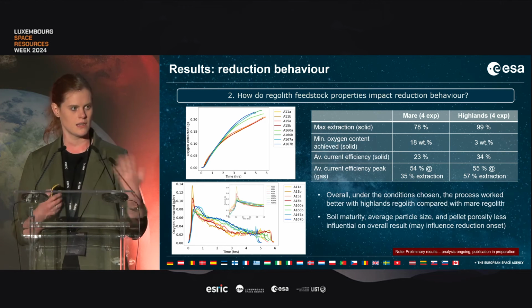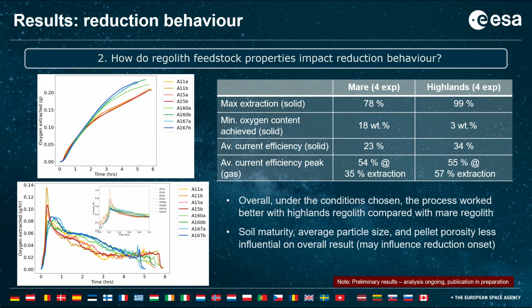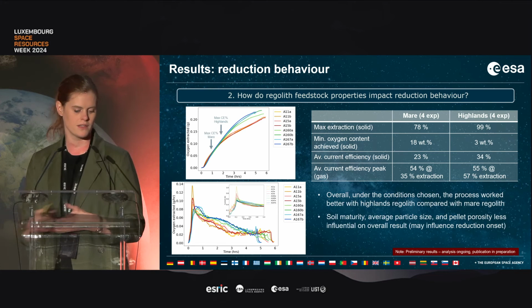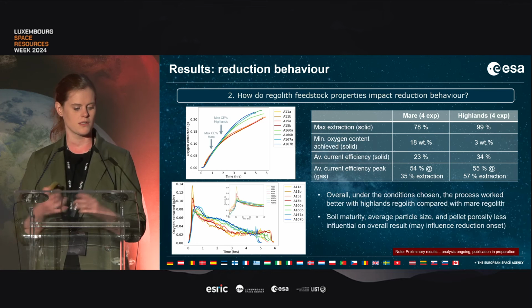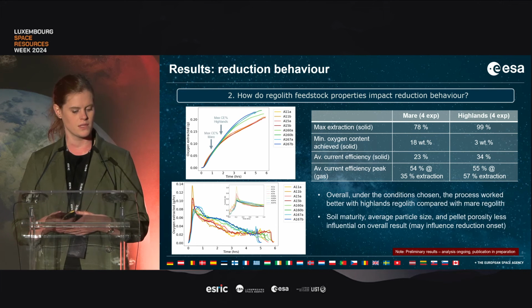Here we can really see the difference between the Mare material and the Highlands material, where the maximum extraction we got was 78% as opposed to 99%. The minimum oxygen content achieved in the solid material was much higher. The average current efficiency was about 10% lower across the entire experiment duration. And when looking at the peak of the current efficiency achieved throughout the experiment, that was around the same, 55% for each type, averaged across all 4 of the runs. However, for the Mare material, this occurred much earlier in the experiment. So it means that for the Highlands material, we can get a lot more oxygen out before the efficiency drops way off at the end. Overall, under the conditions that were chosen, the process worked better with Highlands material compared to Mare material.